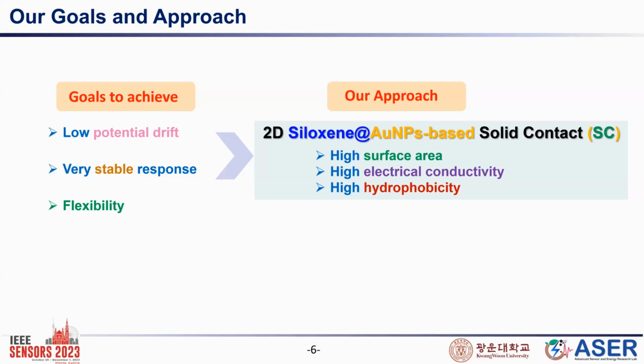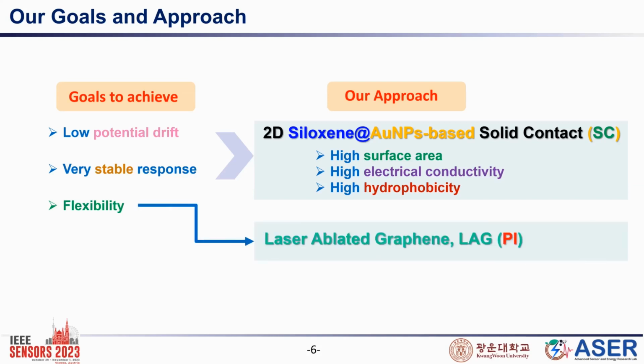As I already mentioned, it gives us good surface area, electrical conductivity, as well as hydrophobicity. The hydrophobicity comes from the 2D-Siloxene, which is a well-known hydrophobic material. And the flexibility comes with laser-ablated graphene. We have taken PI, polyimide film, and with the cost-effective and facile method of fabricating LAG, just laser scribing the PI film. Also, it acts as a substrate or current collecting layer, right?